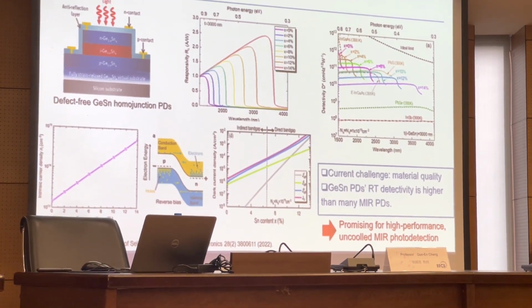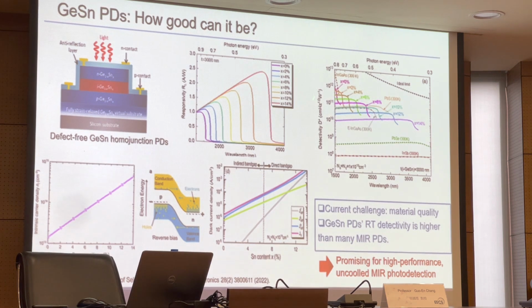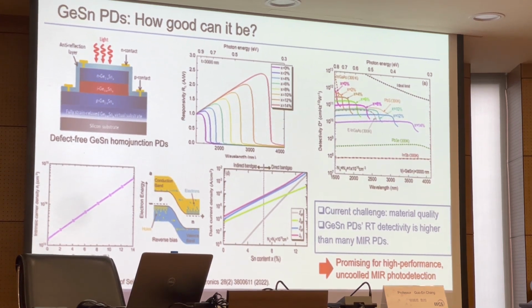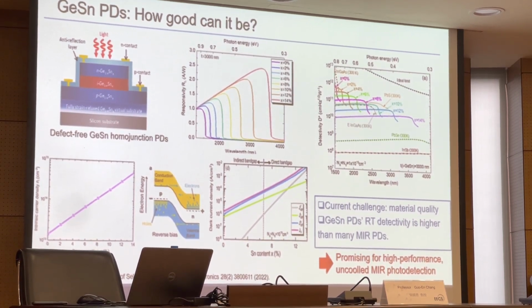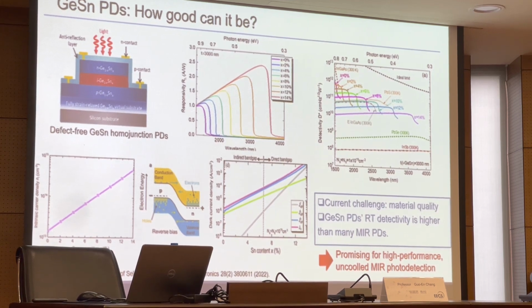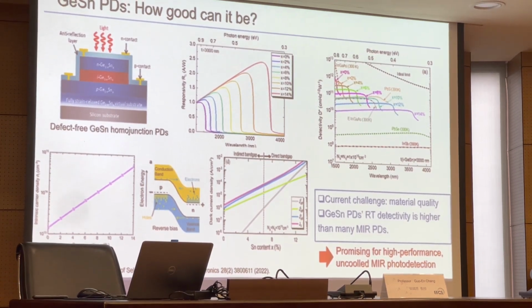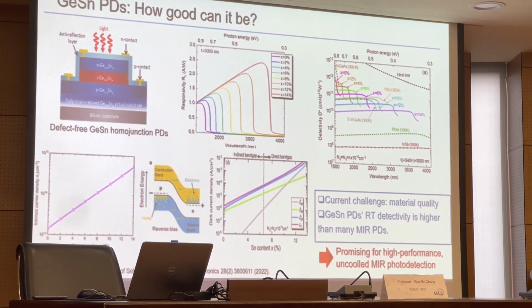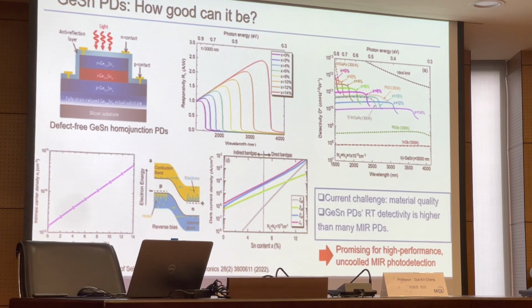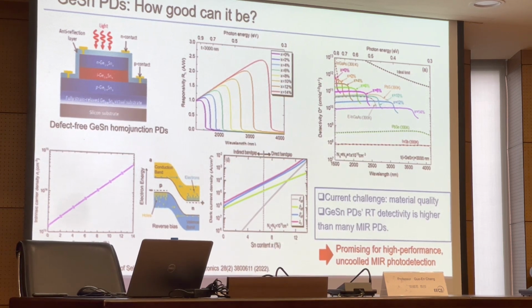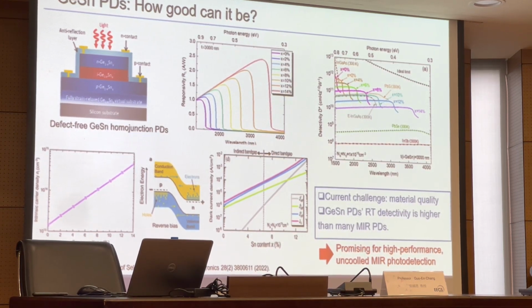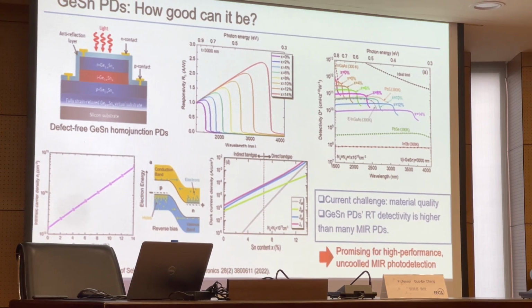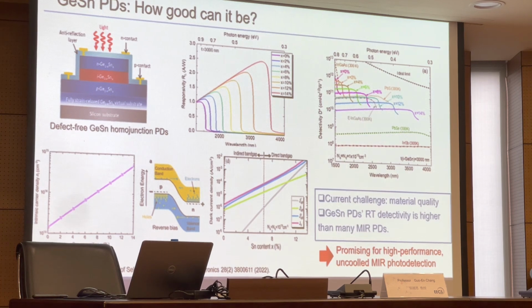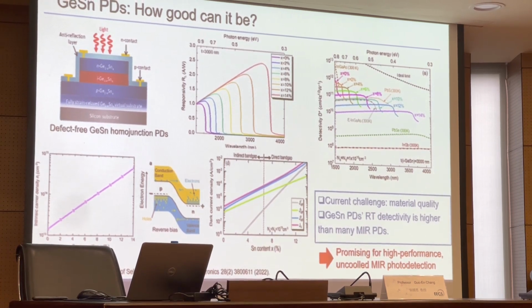When we compare the detectivity, we find that when we increase the tin content, the responsivity spectrum and the photo detection range increase, but at the same time the dark current density also increases. So eventually the detectivity will drop a little bit when we increase the tin content, but the detection range can cover the mid-infrared range.